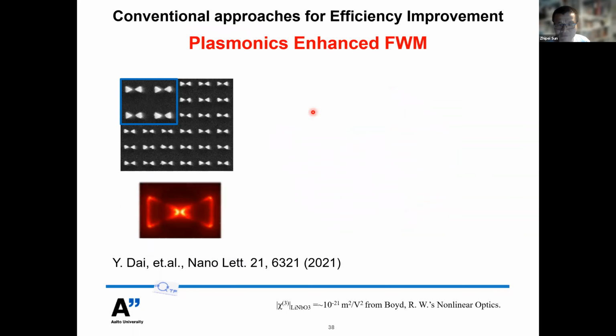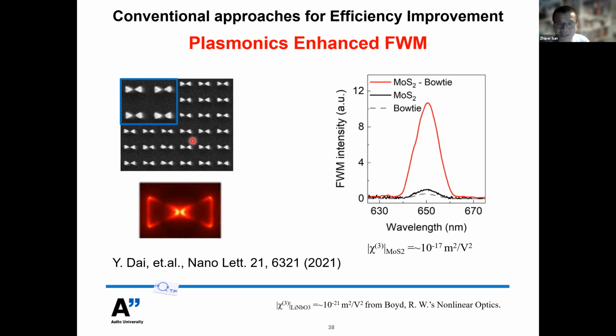Here, I'll give you a few examples of what we tried. This is the example where we used plasmonics, which has a very strong light confinement, to improve the light matter interactions. So here, these are the different plasmonic bow tie nano antennas. We fabricated the different bow tie nano antennas on top of the MoS2 monolayers, and then we looked at the nonlinear response. For example, you can see here the pure bow tie structure, the 4-wave mixing signal, and also the pure monolayer MoS2 devices.